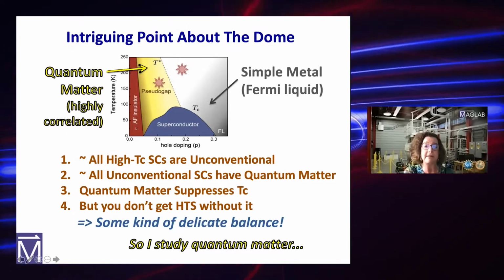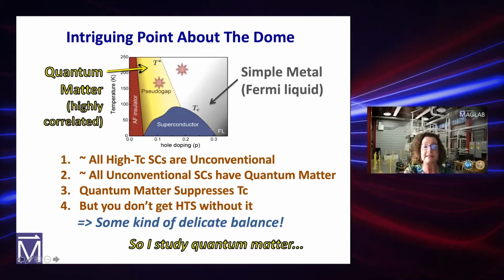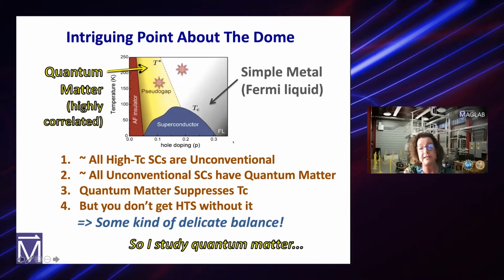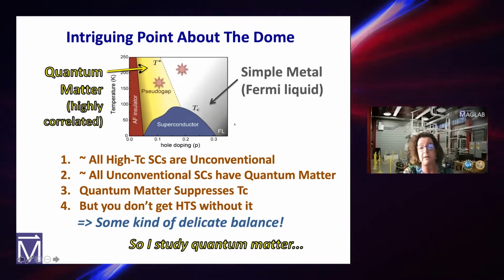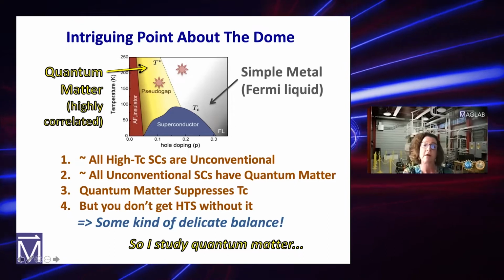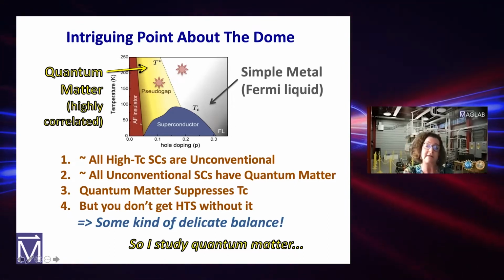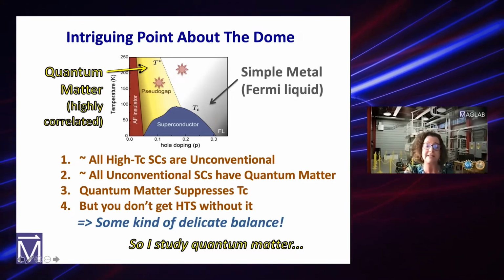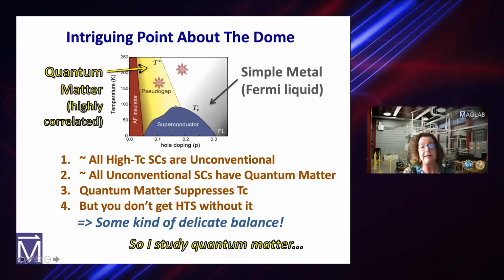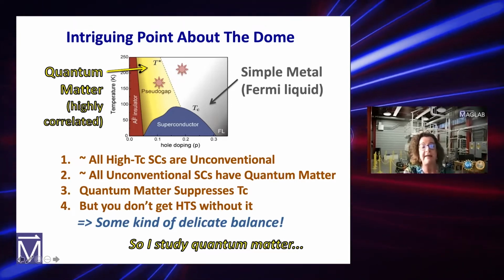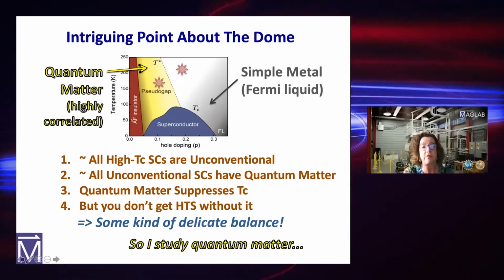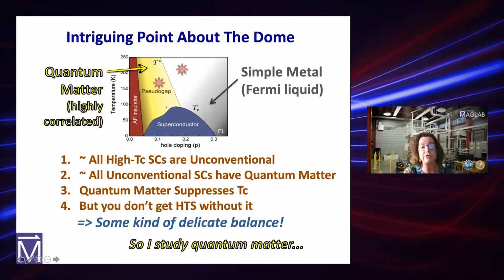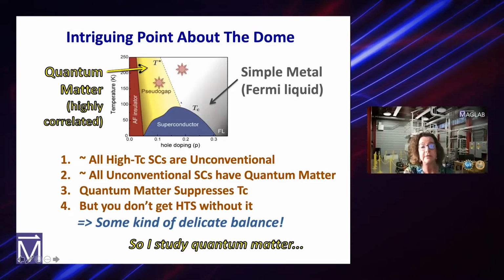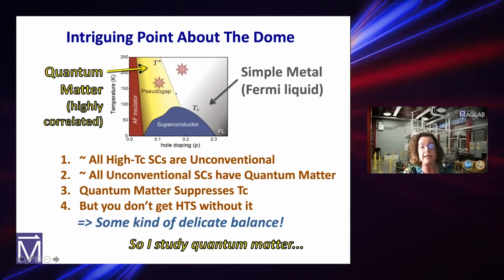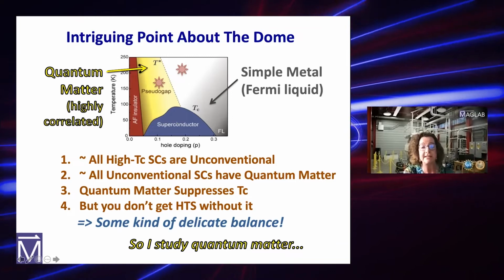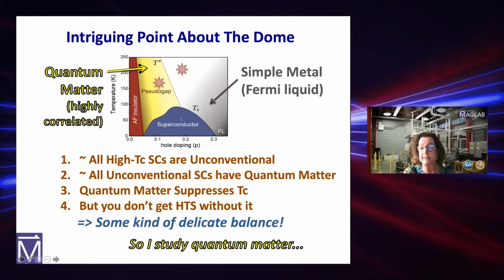Because if you think about it, and I'm not the first person to say this, you have a dome, so you have lower TC on the right side when it's a Fermi liquid, or weakly correlated. When it's strongly correlated on the other side of the dome, TC is lower, and in the center, it's higher. So it looks like these strong electronic correlations are bad for superconductivity, but you don't get high temperature superconductivity without them. So it's some sort of interplay between the correlations above the dome and superconductivity. And what is that delicate balance?